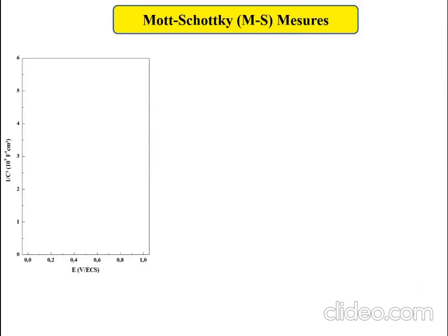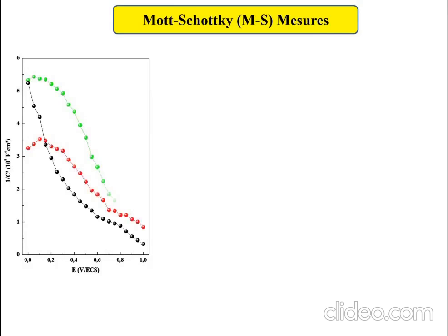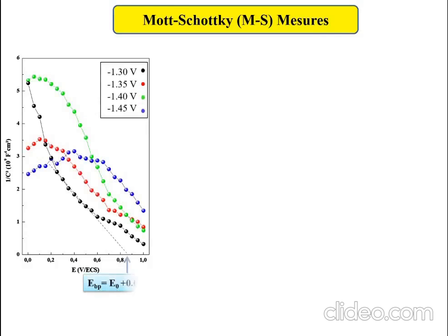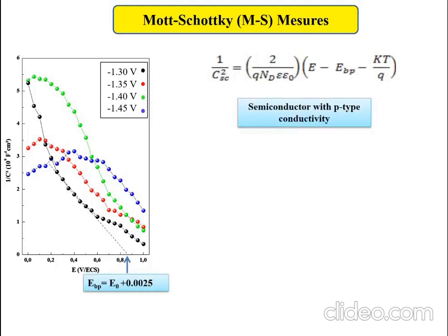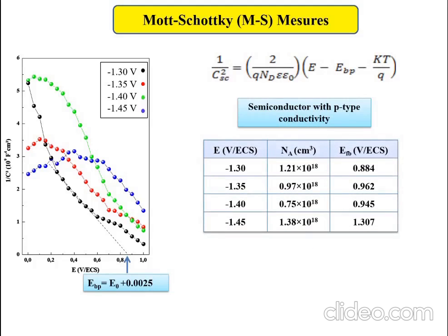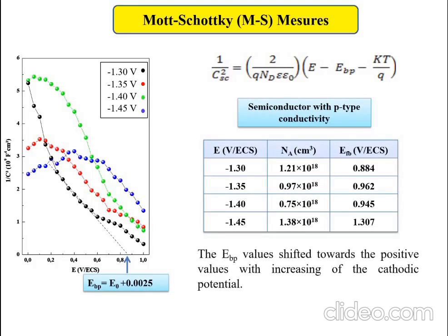Mott-Schottky measurements were used to identify the semiconductor type and the carrier density value. The negative slope of the curves indicates that all the nickel oxide thin films are p-type semiconductors, with the carrier density varying irregularly between 0.75 and 1.38.